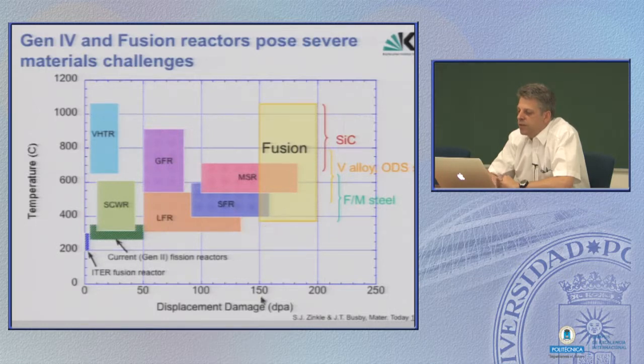As said, a fusion power plant would require 150 to 200 dpa, and temperatures starting from 400 °C as high as possible. As high as possible means we can cover at the moment with ferritic martensitic steels, which could be produced on a large scale, temperatures up to about 550 °C. There are plans to increase this temperature also with steels, but then somewhere between 600 and 700 °C there is a natural end where steels can be used.